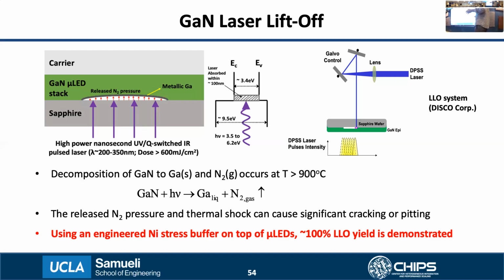In this work, we have tried to model the LLO process itself and come up with an engineered stress buffer, which we put on top of the LEDs so as to improve the yield of the LLO to almost 100%. The image on the right shows the typical setup that we use for this GaN LLO process, which is done at DISCO in Japan. A Q-switched solid-state laser is used, and the third harmonic, which is 355 nanometer, is shone on the sapphire substrate using galvo control. It creates Gaussian beam spots on the surface, which are then raster scanned using this control system. So any questions about the process?